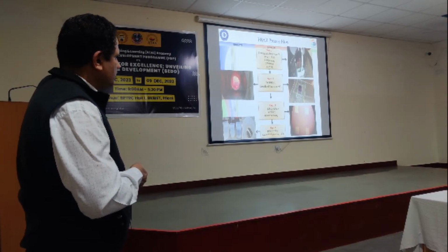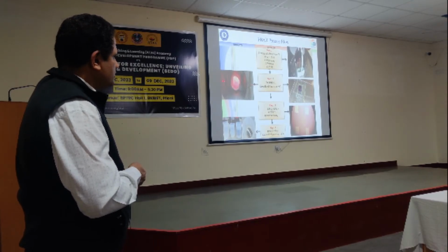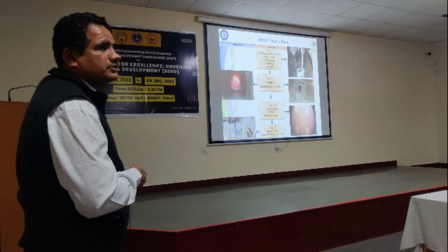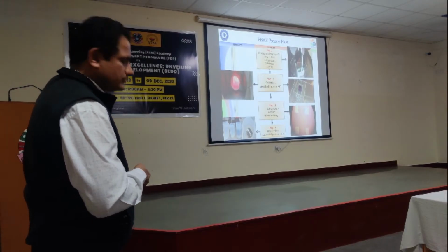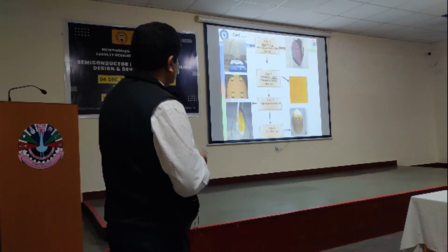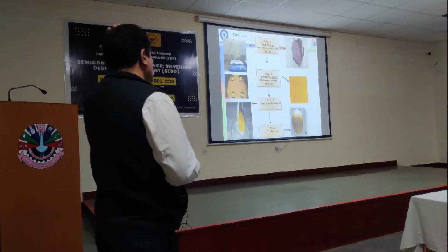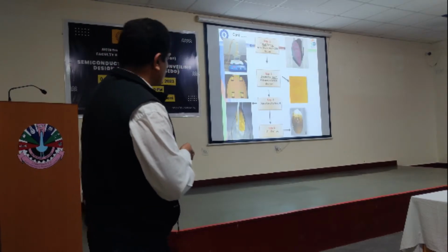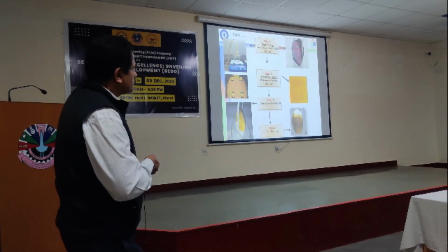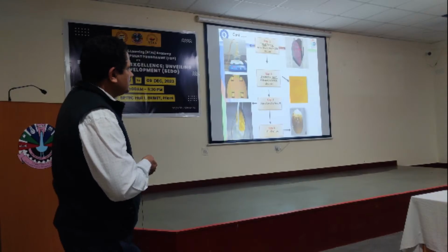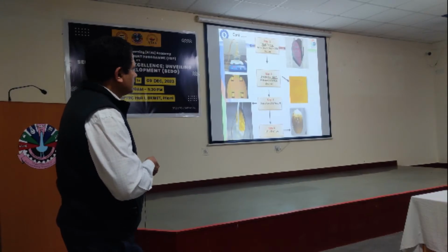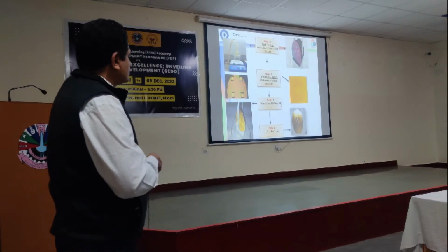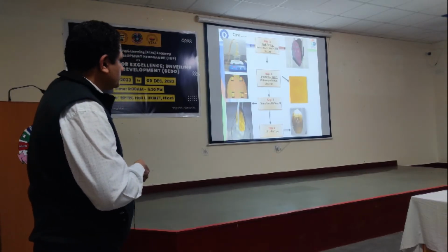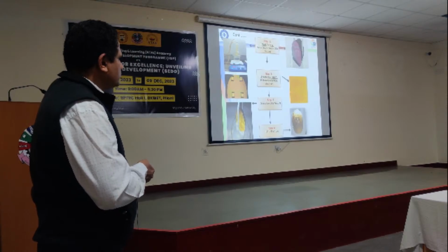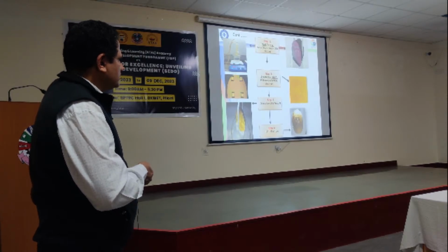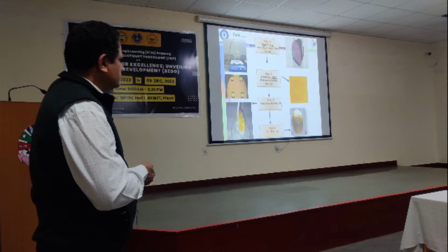Here you see the wafers, oxidation done at a very high temperature, 1100 degrees Celsius. So this is just to give you a feel of how the wafer looks after every processing. You see the wafers, some cavities and patterns are made here. Then the cavities look like this under the microscope. Then some gold layers are deposited and then the patterning. Then the lift-off was done.